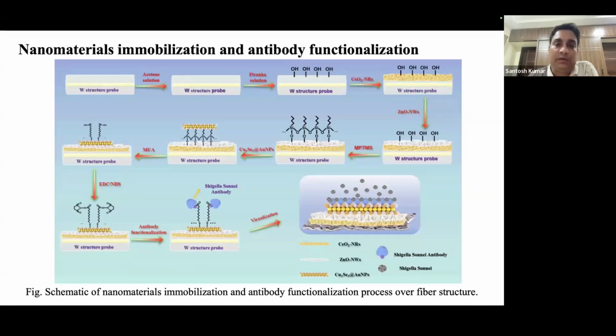Similarly, for the antibody functionalization, we dip the nanoparticle-coated fiber into NaOH solution for 5 hours, which creates the carboxylic group. After that we dip it into EDC NHS, which activates the carboxylic group. After that we dip the fiber structure into the antibody solution.